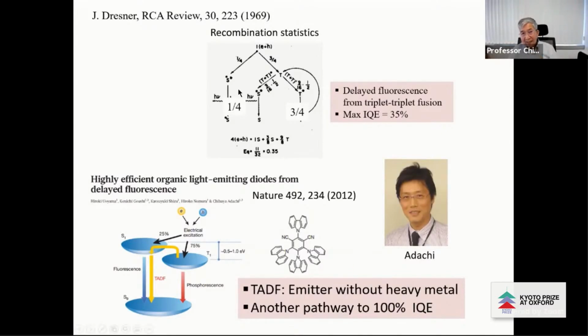In fact, when you look back in 1969, there's a review. That was the time that people were working on organic electroluminescence. They already observed the delayed fluorescence from triplet fusion, in other words, two triplet molecules come together and then produce a singlet to give you the high efficiency. But Adachi's method is that they can design the molecule in such a way the triplet is almost degenerate with the singlet, so that they can go back from here and go to the singlet and then come down as the fluorescence.